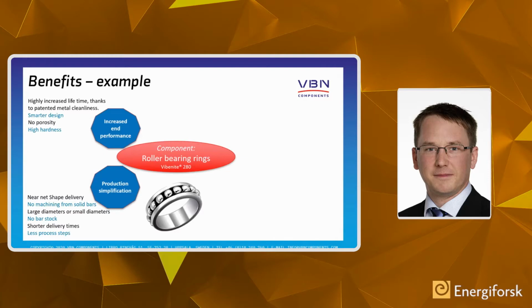Then you simplify the production, and of course, if you need a highly alloyed material today, you need to buy a bar. And to do a ring from a bar, you need to remove about 90% of the material. And the higher the hardness and the higher the wear resistance, the more difficult it is. But buying from Vibenite, you can get a ring. And you can also get a small ring diameter or a large ring diameter. And that is something that is totally not possible today. You cannot buy a very, very big bar in extremely highly alloyed material and remove the material to make a ring. You don't do that. So, in general, it's the fewer process steps that are the big thing.